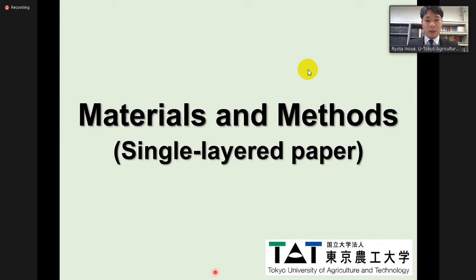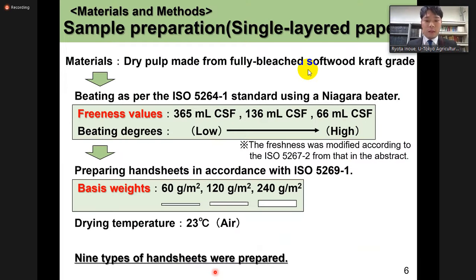First of all, let me talk about single-layered paper. We used dry pulp made from fully bleached softwood kraft grade as the raw materials. The kraft pulp was beaten into disintegrated pulp using a Niagara beater. Samples were taken when the freeness reached 365, 136, and 66 milliliter CSF. Here, the freeness was modified according to the standard from that in the abstract. The lower the value, the higher the beating degree.